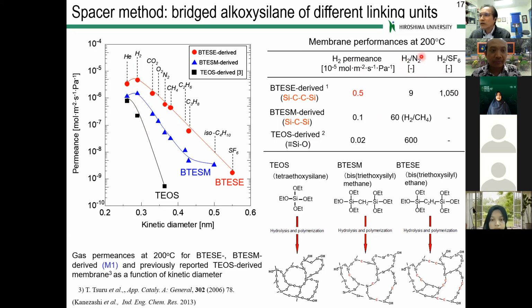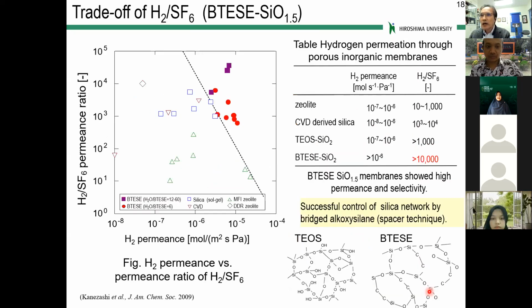But when you look at the hydrogen over nitrogen selectivity, the selectivity decreases from 600 to 60 and around 10. But this BTESE-derived membrane still keeps the high selectivity of hydrogen over SF6, which is the largest gas, 5.5 angstroms. So we would like to say there are no pinholes in the case of BTESE. So this decreased permeance should be due to the controlled pore size. Now this is the trade-off of hydrogen over SF6, okay? So this is called the trade-off.